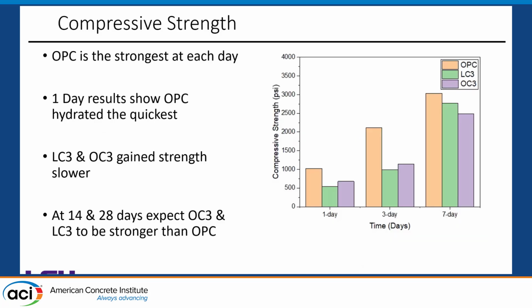With these 3 binders, we conducted compressive strength tests on them. You can see there's a very noticeable difference at the 1-day strength, where the blend with ordinary Portland cement is much stronger. This is to be expected as LC3 and the OC3 rely on a pozzolanic reaction, which does take longer to occur. That's why even on the 3-day, the OPC is still much stronger.